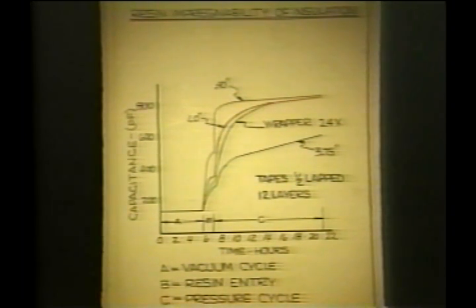Now, if you look at the A section of the curve, which is the vacuum cycle, for the first few hours, the capacitance doesn't change because it's in the normal vacuum extraction process to remove the air and the volatiles from the system. At that point, the B part of the cycle starts where the resin is admitted to the system and starts to penetrate the insulation, and the capacitance starts to increase. And then finally, after the soak at atmospheric pressure, the pressure is increased to approximately 100 pounds per square inch, as in the typical VPI cycle, and completes the impregnation process.